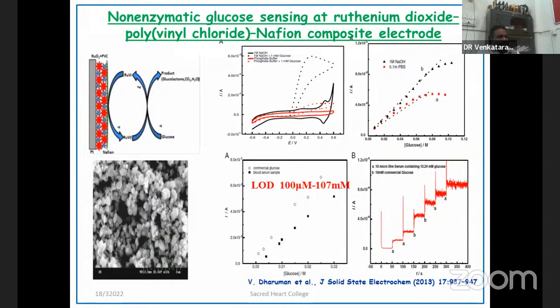So what we did was we prepared ruthenium oxide by thermal annealing from ruthenium chloride, mixed it with tetrahydrofuran solvent, and put it on the electrode surface. This mixture consisted of ruthenium oxide and polyvinyl chloride as a binding material, because without binding, the stability of the ruthenium oxide on the surface is quite difficult. So we integrated ruthenium oxide along with PVC, which is completely soluble in tetrahydrofuran. By mixing this and drop casting, it forms a film, and this film reacts with glucose to produce gluconolactone, or it undergoes further oxidation to give carbon dioxide and water.